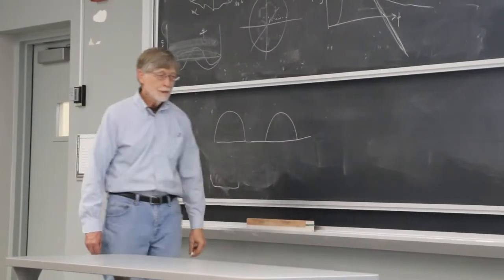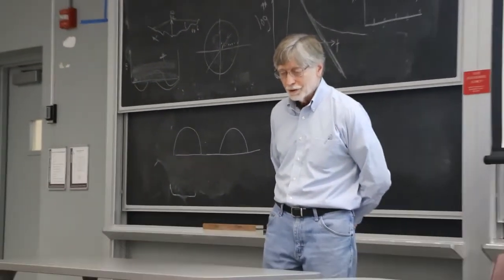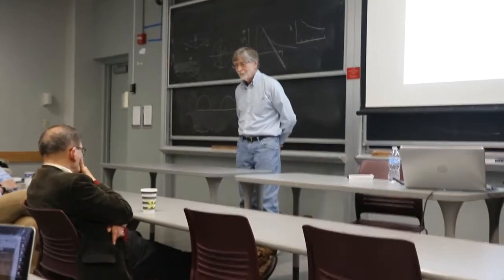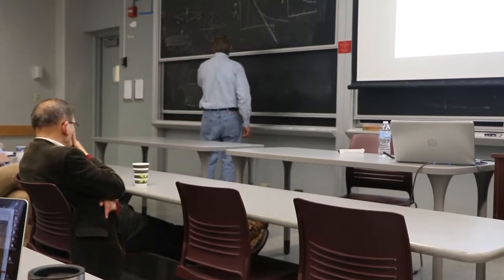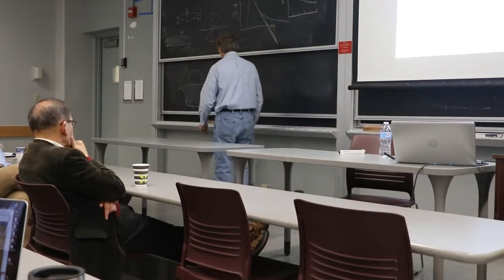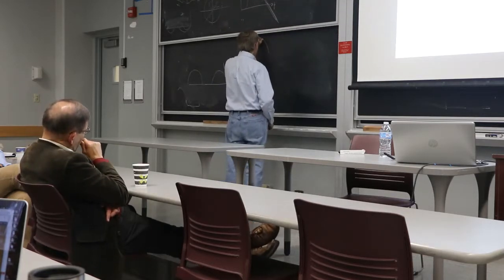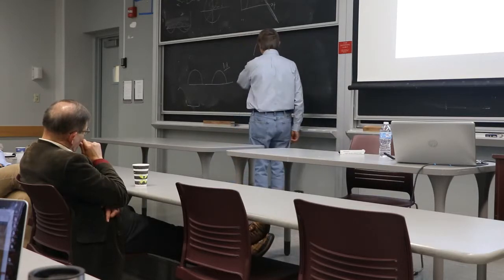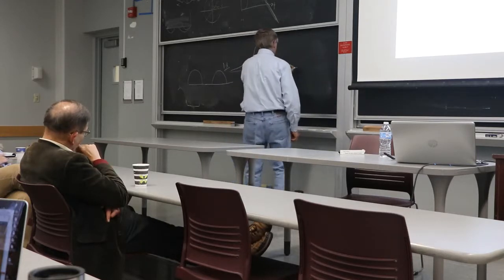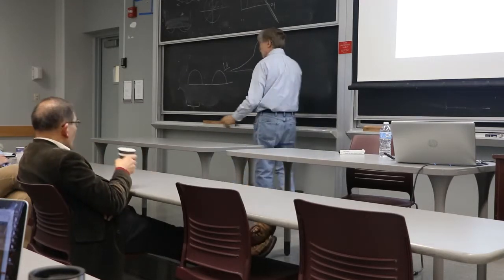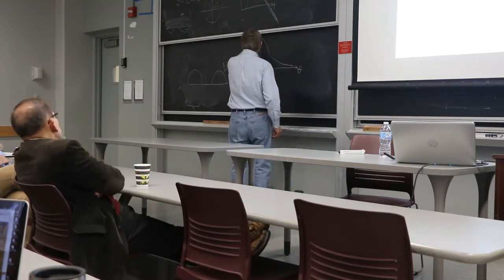Okay, so it turned out that a guy named Stewart measured all the metals in 1950 or something, 58 maybe. Every metal, he measured all of the 1-dimensional parabolas, and they look like this. So there's your parabolic part, which is the free electrons, and then there would be a great big tail like this, which is the core electrons. So this is theta, that's the angle between the two photons, and this is the number of counts.